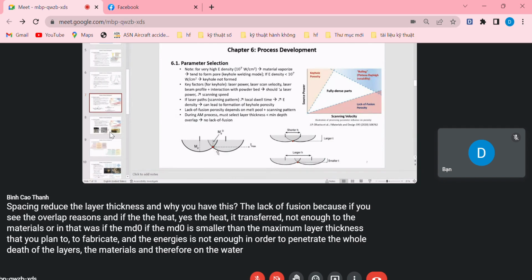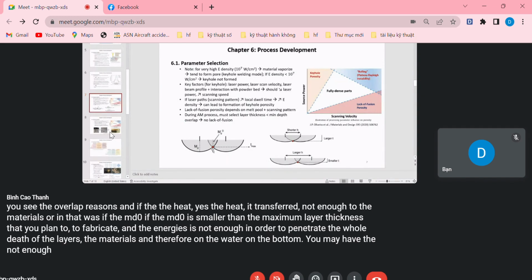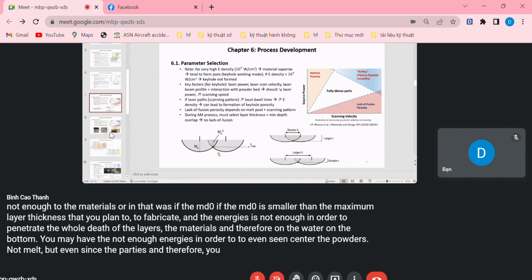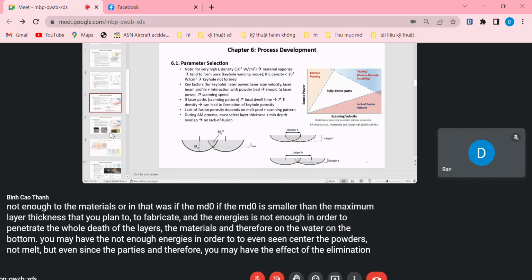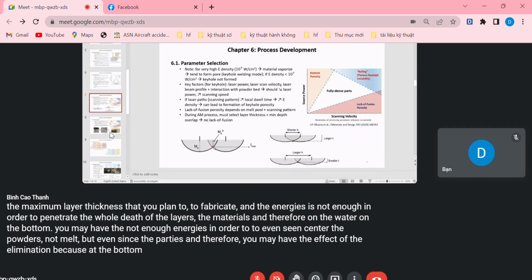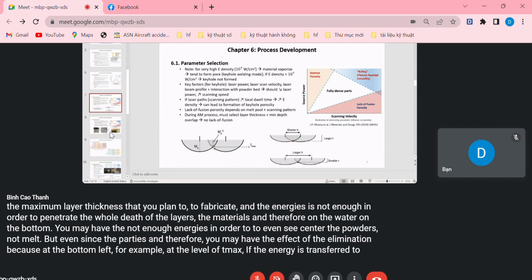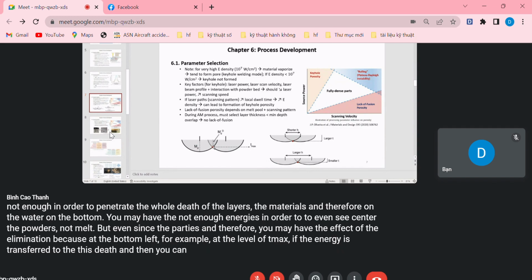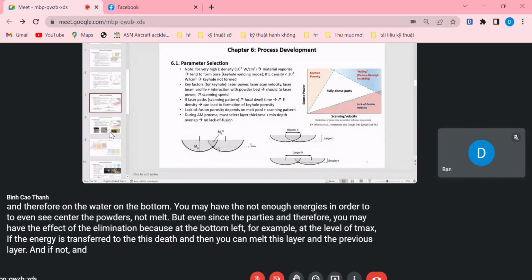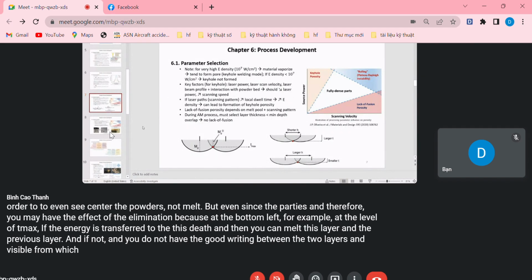And therefore, at the bottom you may have not enough energy to even sinter the powder, not melt but even sinter it, and therefore you may have delamination. Because at the bottom, for example at the level of Tmax, if the energy is transferred to this depth, you can melt this layer and the previous layer. If not, and you do not have good wetting between the two layers, this is a problem which may lead to material delamination.